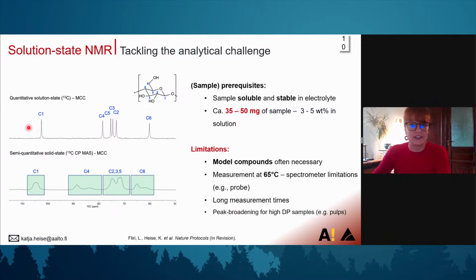There are some limitations. So if we study reaction chemistry to understand that and to properly assign the signals, we very often need model compounds. We use for that cellobiose or glucose. Then the measurement and also the dissolution of the cellulose is carried out at 65 degrees, which can be a challenge for the samples, but also for the spectrometer.